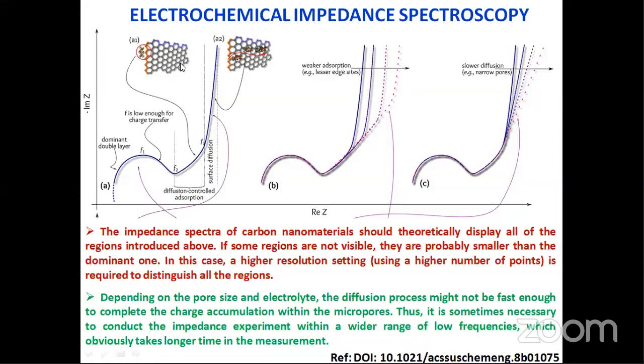It depends on the porous nature of the electrode material. The adsorption mainly depends on the porous nature. Say, for example, if you have this impedance behavior, and if this low frequency spike always tries to go near 90 degrees. If it goes to an inclined angle of nearly 40 degrees, it means adsorption is weaker, but at the same time the slow kinetics will happen. So from the impedance analysis we can directly determine whether the charge storage mechanism is adsorption, desorption or diffusion based process, or a mixed process. Everything can be obtained from the electrochemical impedance spectrum.